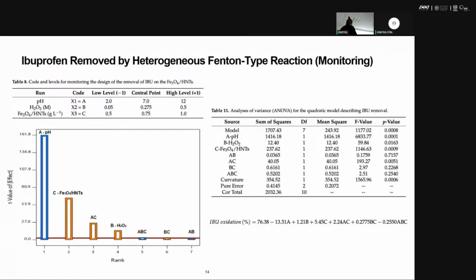So this study gives me the Pareto plot, and even more, the empirical equation for this method. As I say, in the Pareto plot, the pH is the main variable for the absorption. It is blue because it means that it must be reduced to improve the absorption, which means that it works better in acid condition. And then we have the absorbent material.